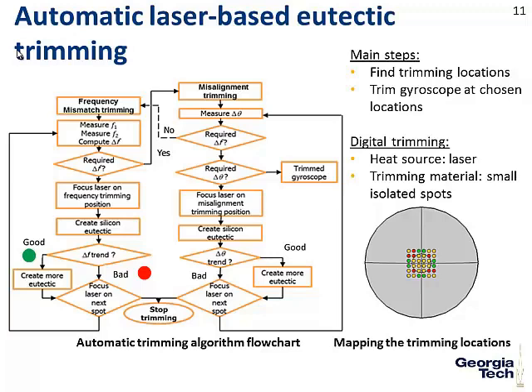Also, once you find those locations, I didn't draw them, but they are between the green and the red, are locations where the frequency split actually didn't increase or didn't decrease. There was no effect on the frequency split. What's important is that if you melt gold or aluminum there, the frequency split doesn't change, but the orientation of the modes does change. So if, for example, your mode is not exactly aligned on your electrodes, by using those locations, you can actually move your results. But I don't have any result in those slides. I have them in the paper.